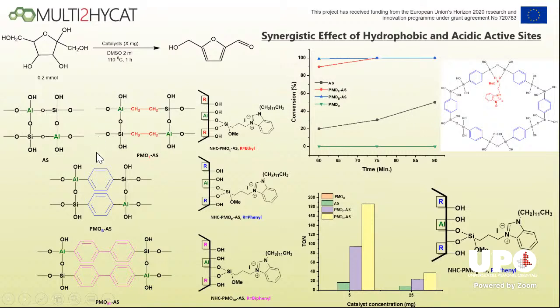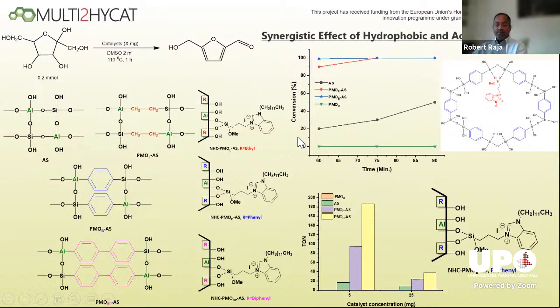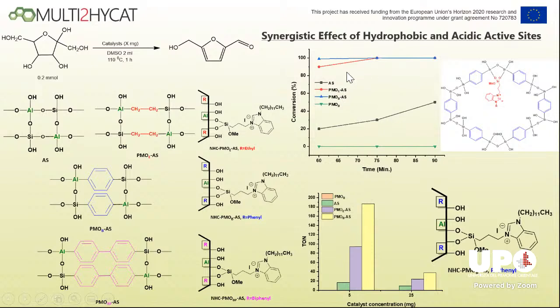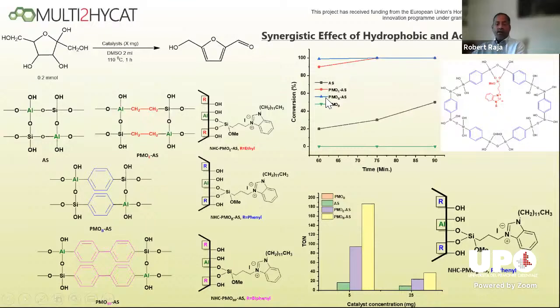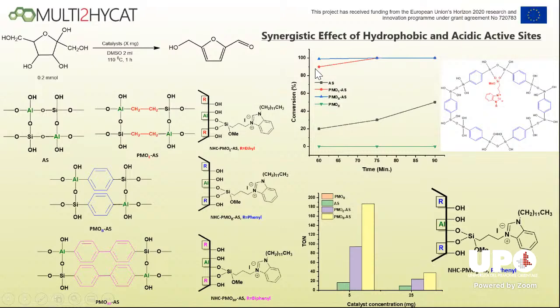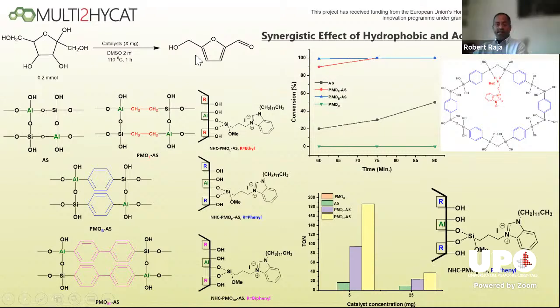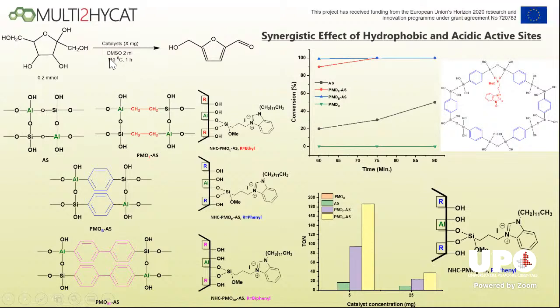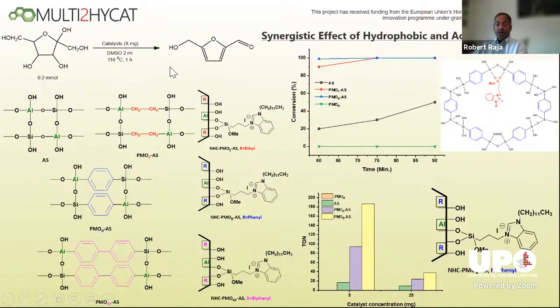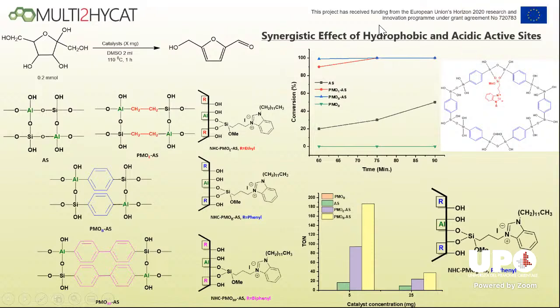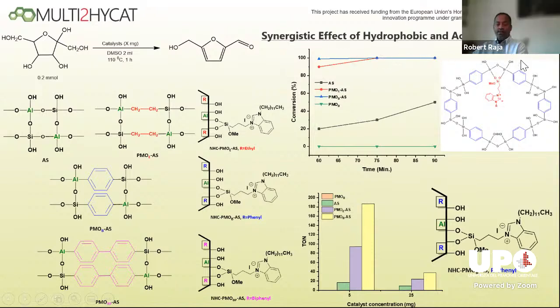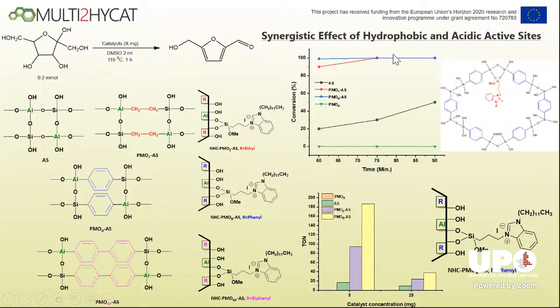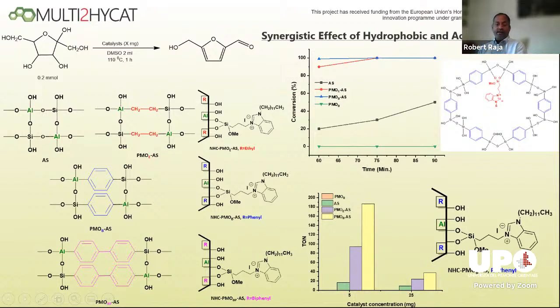Using purely acidic materials, such as these aluminosilicates, gives you some activity, but this is quite low when you look at traditional zeolite-based systems. And then we are introducing here these hydrophobic moieties in addition to these acid sites. And one can now see that when you do these with both the PMO having the ethyl groups or the PMOs having the phenyl groups, the catalytic activity is significantly enhanced at temperatures as low as about 100 degrees. Now, this dehydration is normally carried out with zeolites at quite high temperatures, but when you introduce this synergistic phenomenon with the hydrophobic sites in close proximity to these acid sites, we see this huge enhancement and stabilization in the catalytic behavior.